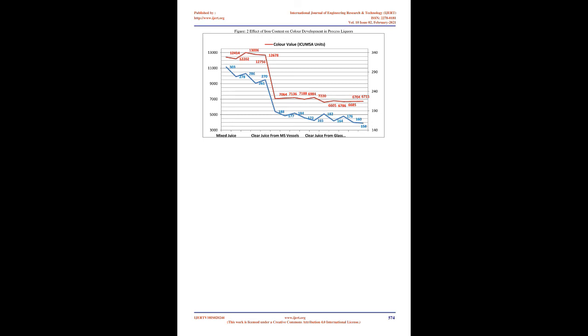Data presented in Table 3 and Fig. 2 indicated that for a given quality of juice, keeping other variables constant, the iron content is more in the juices which were processed in mild steel vessels than in the juices processed in glass vessels, and so is the color development. Thus it may be inferred that the formation of coloring compounds as a result of reaction between iron and polyphenols may alone increase the color values of clear juice by 5 to 7%, which in turn on crystallization may enhance the sugar color by corresponding value.